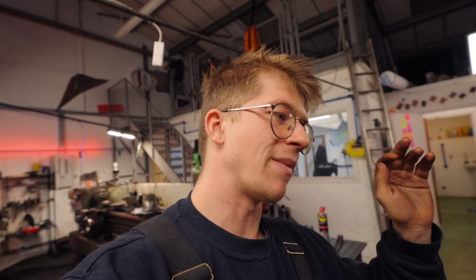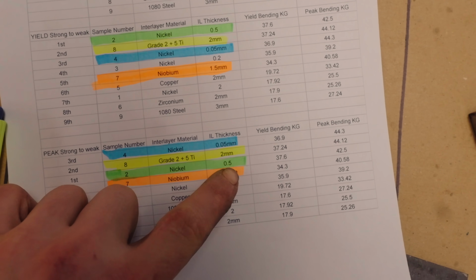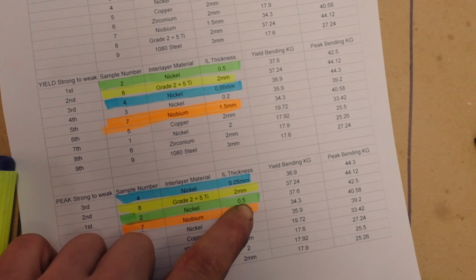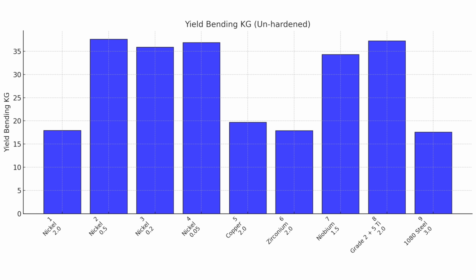And what's cool to see is that it looks like we have 2 competitors in terms of the best interlayer, just switching back and forth on their max peak force and their max yield force. Our 0.05mm nickel interlayer and our 0.5mm nickel interlayer, they both performed really well.